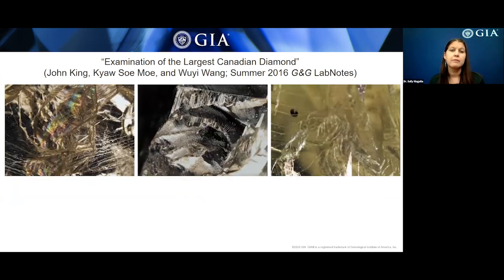On this slide, we're showing several photomicrographs of that 187 carat diamond crystal. One side of the diamond had iridescent color banding due to light interference along cleavage planes, and you see that on the left image. In the center, we see that the stone showed irregular morphology with several different cleavage faces. Also, some of the original faces showed dissolution pits. And then on the right, we see a dark, unidentified mineral inclusion that was noted on one side of the rough.